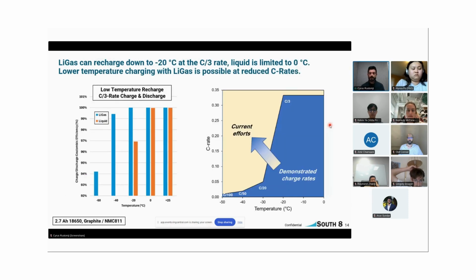So of course, one of our differentiators in the market is our low temperature capability, in case you haven't guessed that yet. There are a lot of people asking for rechargeability down below 0 degrees Celsius, which is the limit for your conventional liquid-based electrolytes. And so we are doing a lot of work with partners right now to demonstrate rechargeability at lower temperatures. And today we've demonstrated essentially a good C/3 charging at minus 20, which is pretty nice. So you can see here a little temperature bar graph.